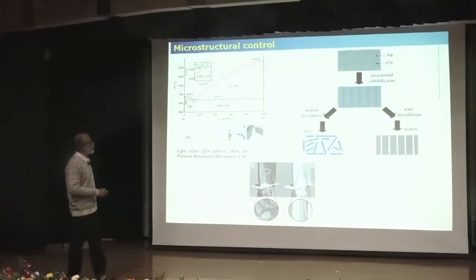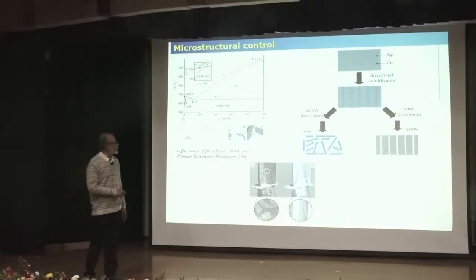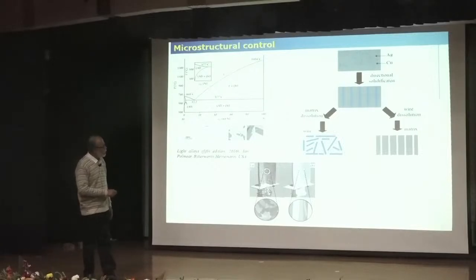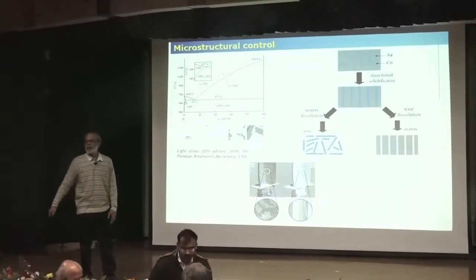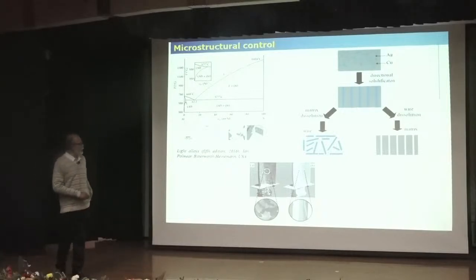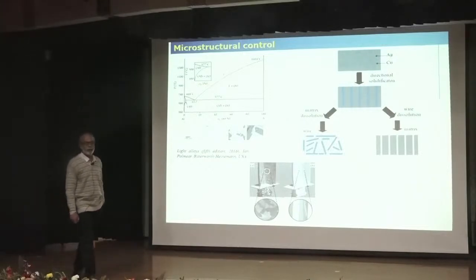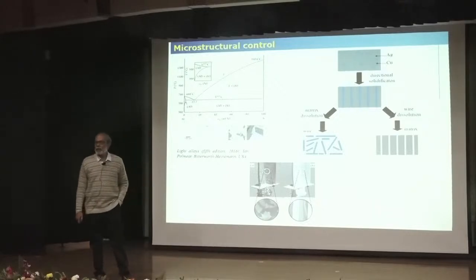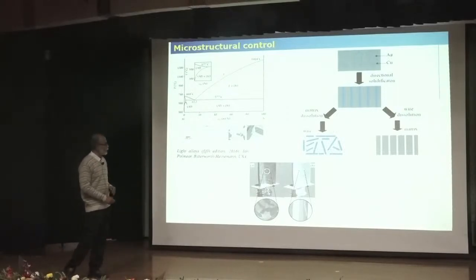Similarly, this is a silver copper eutectic, right? And it is possible to allow this eutectic to form in a directional manner. If you impose a heat transfer in this direction, the two phases, silver and copper, which are mutually insoluble and remain as silver and copper phases during eutectic solidification, you can develop directional growth of these two phases. Now if you remove one of the phases by etching, you can develop nanowires. So this is one of the methods for development of nanowires by engineering the eutectic solidification, or else you can develop nanopores.